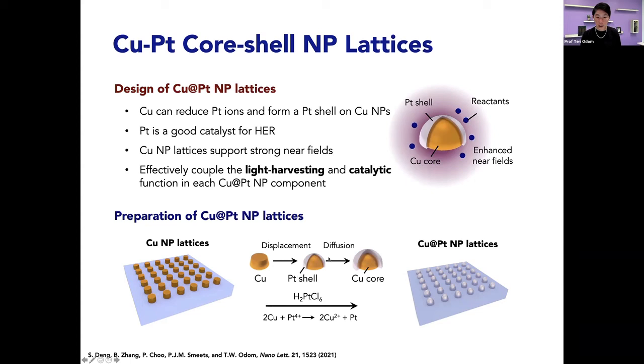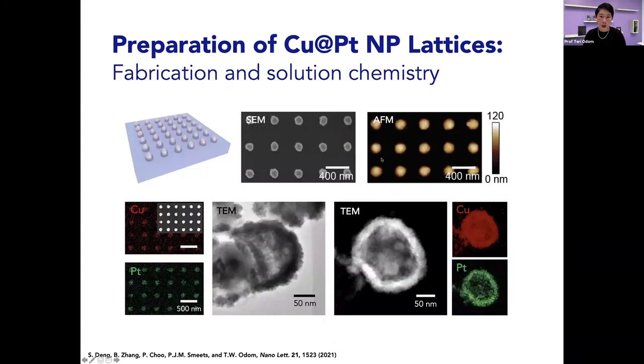to start seeding and growing this platinum shell. And we can model the displacement and diffusion growth. It's fairly straightforward and consistent with what we expect based on the reduction. And so we do get some of these shapes that happen because these are edges that will start to etch in the very beginning. And so the SEM images look reasonable. These TEM images, you can see again the shape. And if we look at the elemental maps, you can see that there's copper throughout the particle, and platinum is mostly confined to the shell layer.